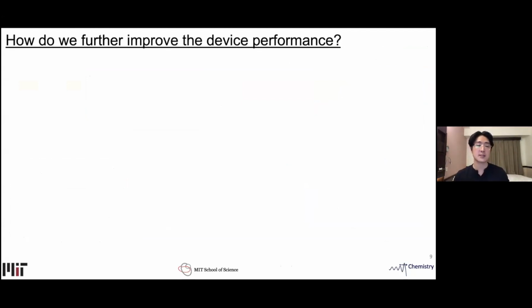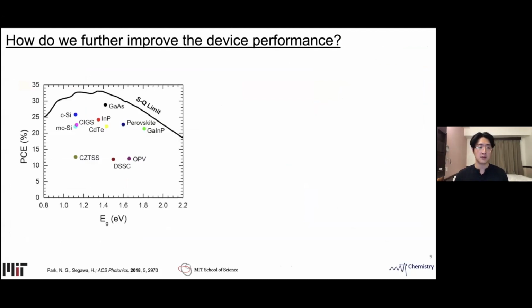In order to devise a plan to further improve the device performance, we first need to see where the efficiency deficit is coming from. On the left, I'm showing a plot of PCE, power conversion efficiency, or how efficiently a solar cell can convert sunlight into electricity, versus band gap. This black trace is the theoretical maximum a single junction solar cell can have, also known as the Shockley-Queisser limit, or SQ limit. The perovskite usually has a band gap of around 1.5 to 1.6, meaning they have a maximum efficiency of around 30 or 31%.